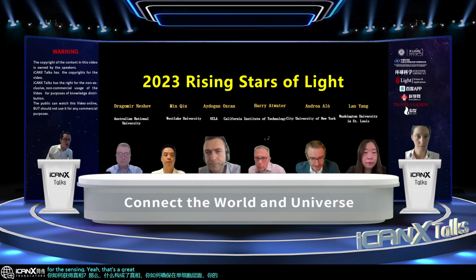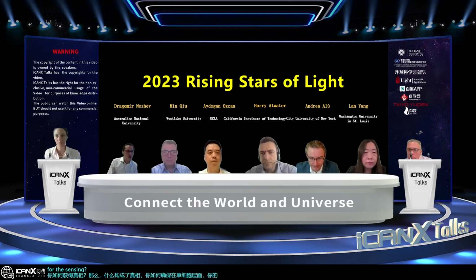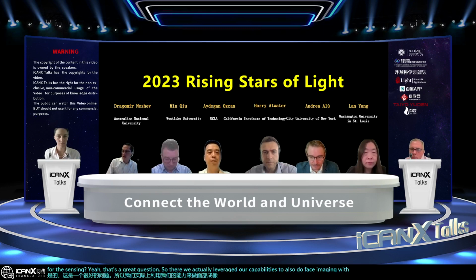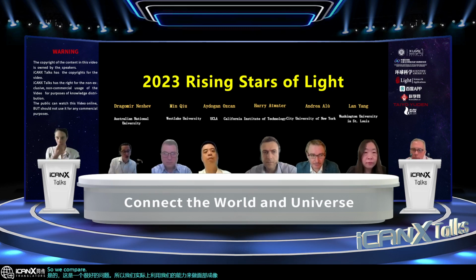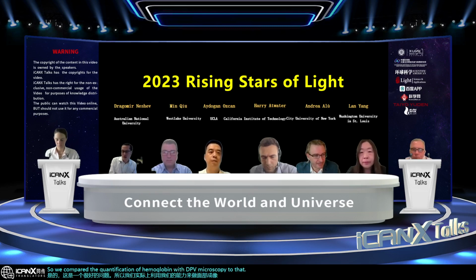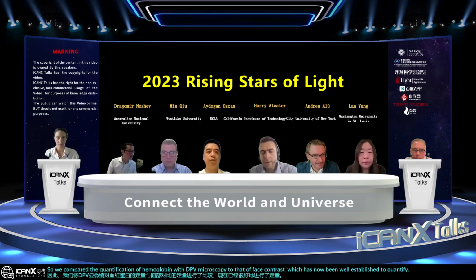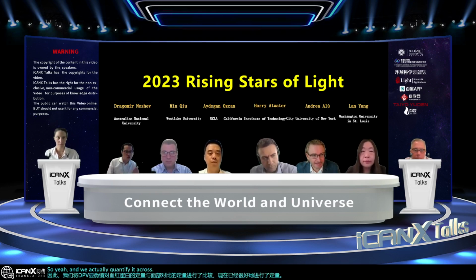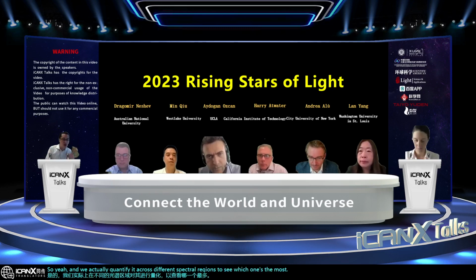That's a great question. So there we actually leveraged our capabilities to also do phase imaging with this interferometric approach. So we compared the quantification of hemoglobin with deep UV microscopy to that of phase contrast, which has now been well established to quantify hemoglobin content. And we actually quantify it across different spectral regions to see which one's the most accurate. And you can do a pretty good estimate with all the wavelengths below 300 nanometers, but there's actually some advantages to using 260, 250 nanometers.